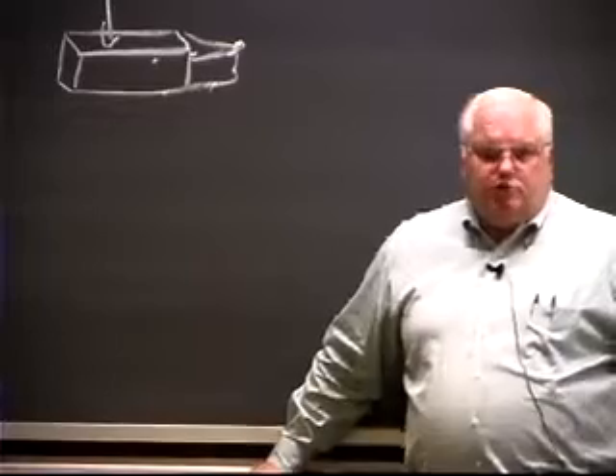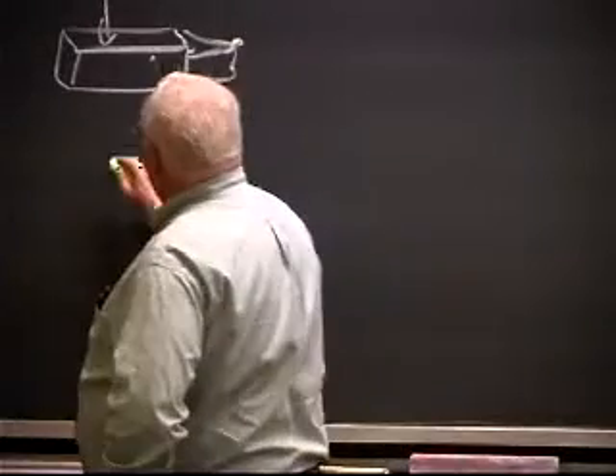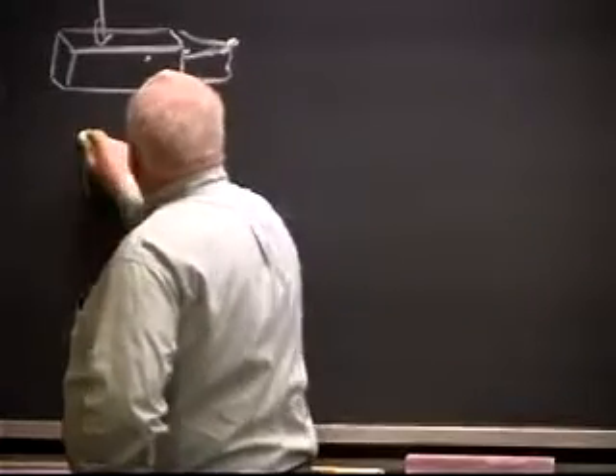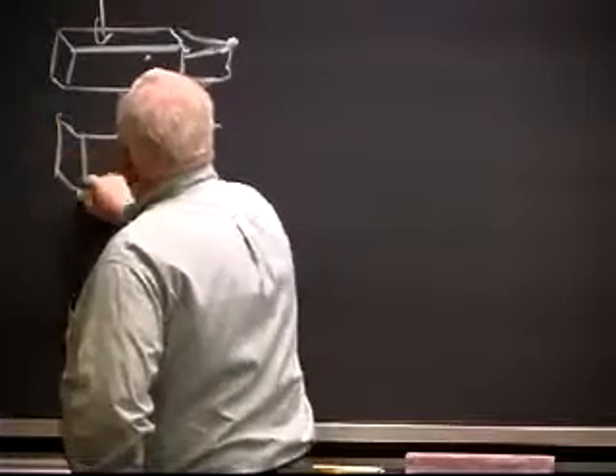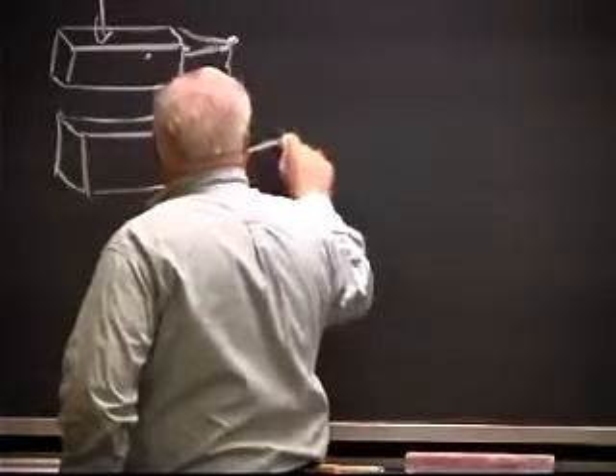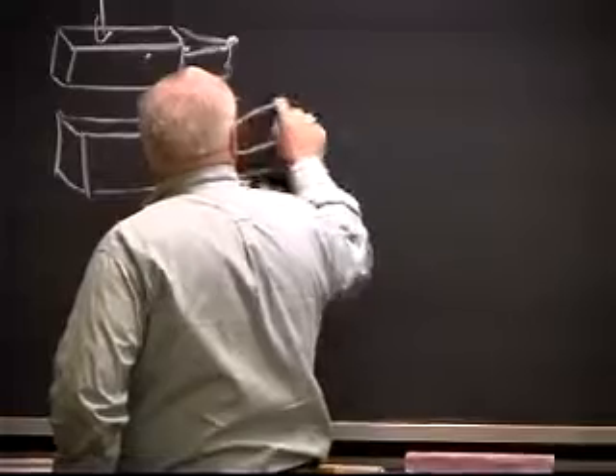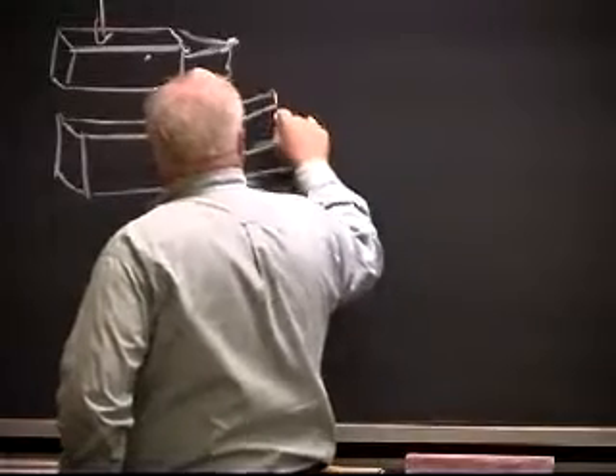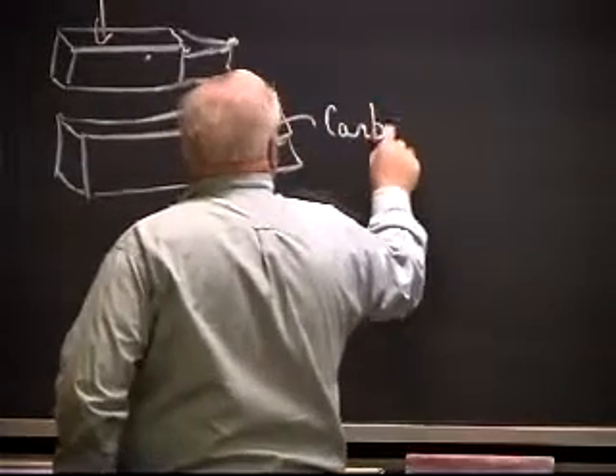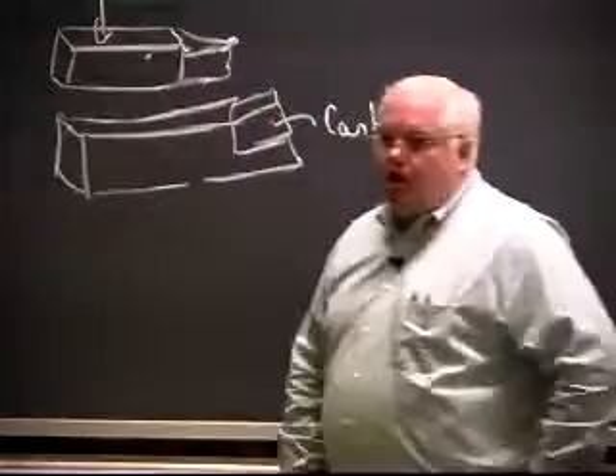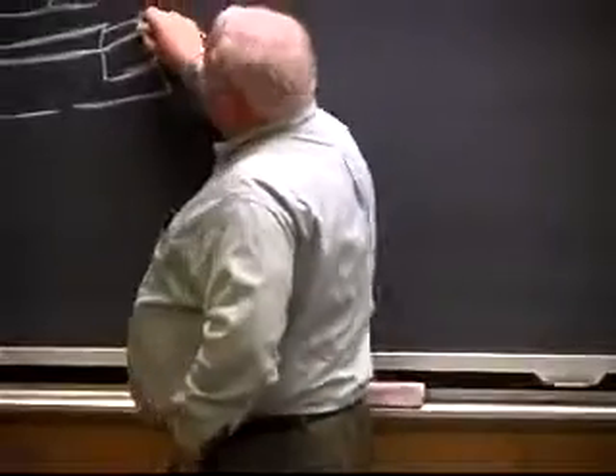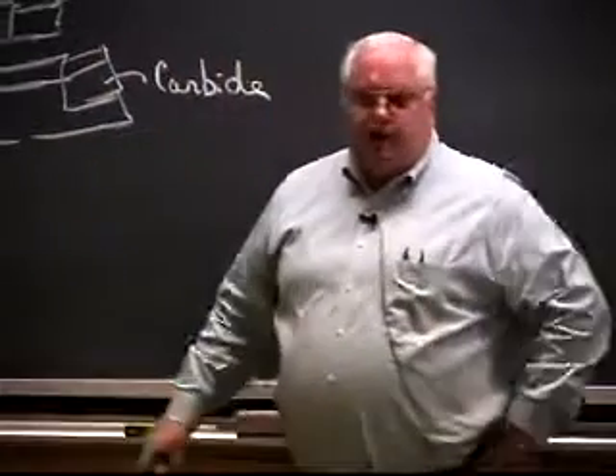And so 30 years ago, when I was a graduate student, they were starting to use insert tools where they had metal inserts or ceramic inserts, whereas a similar type of tool post, but on the end, they basically just had a little ledge, and they would braze a piece of carbide. Well, that piece of carbide can never be more than about 1 centimeter in cross section. Okay? They could braze it, and you can get braze joint strengths of 40,000 psi. And so the carbide's much harder, higher melting temperature, and you could machine maybe 2 or 3 times as fast.